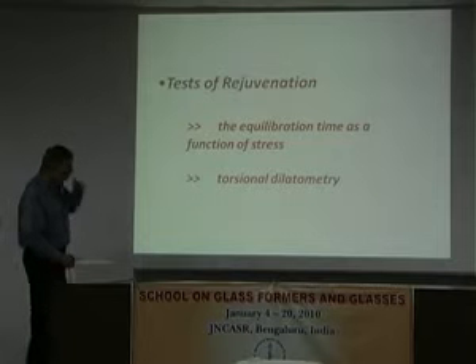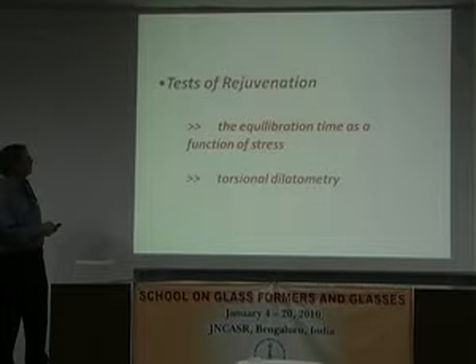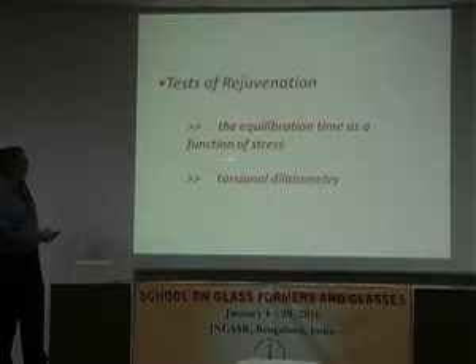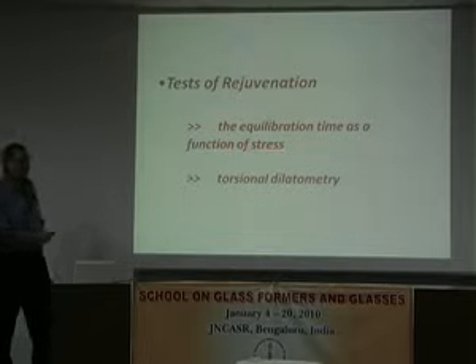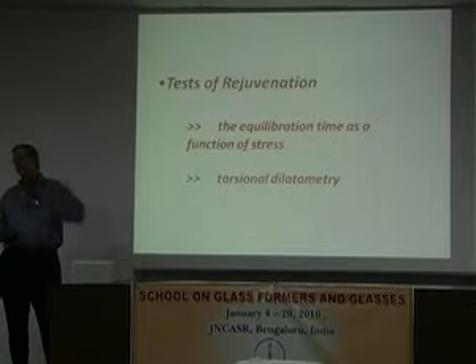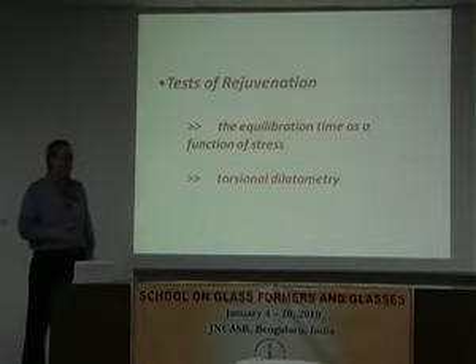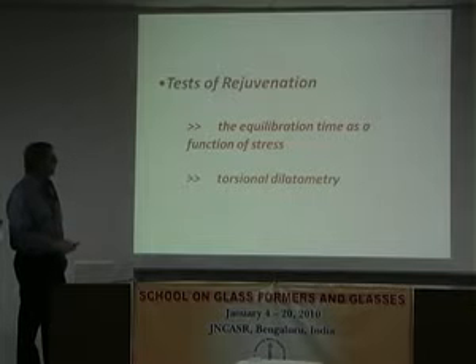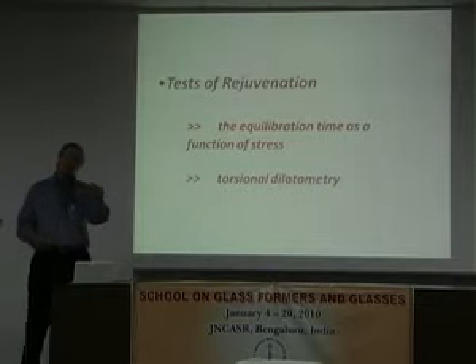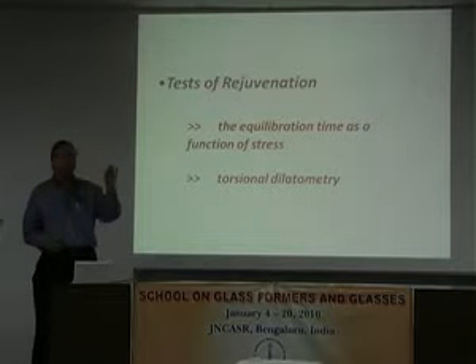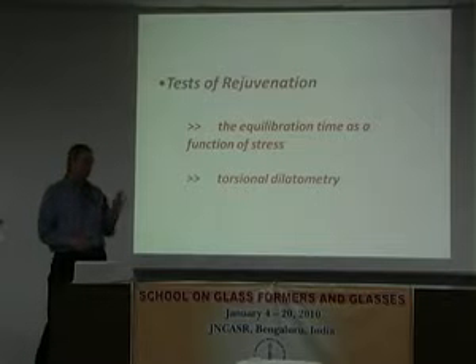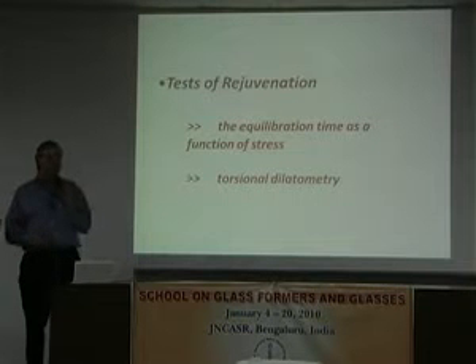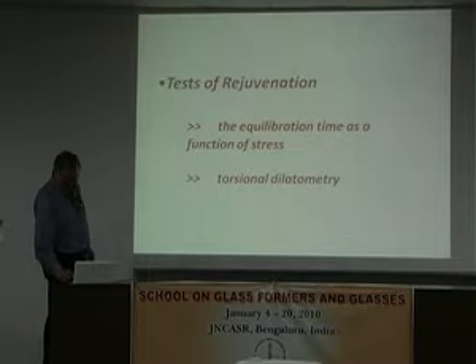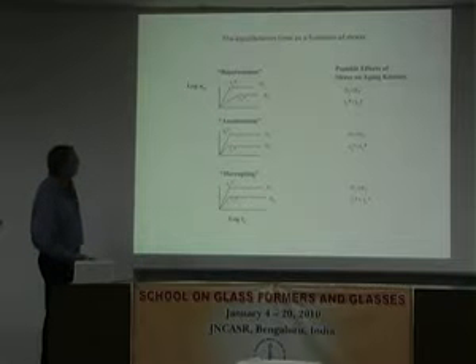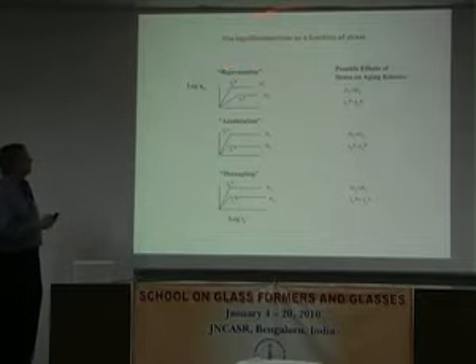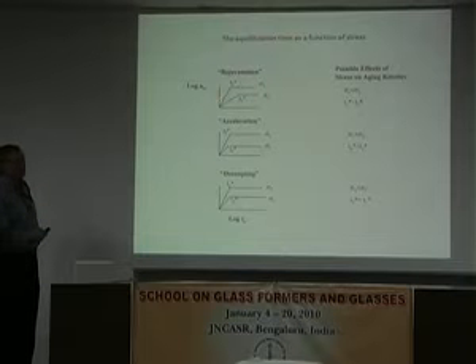So we're going to test this. We're going to do it in two ways. First, we're going to look at the equilibration time as a function of stress, or at least the onset of equilibration time as a function of stress, in our epoxies. And then we're going to do torsional dilatometry to directly look at the measurement of the structure. We could also think about doing torsional calorimetry, but torsional dilatometry is hard enough. Okay, so here's the equilibration time as a function of stress. And remember, if we're close enough to Tg, yeah.